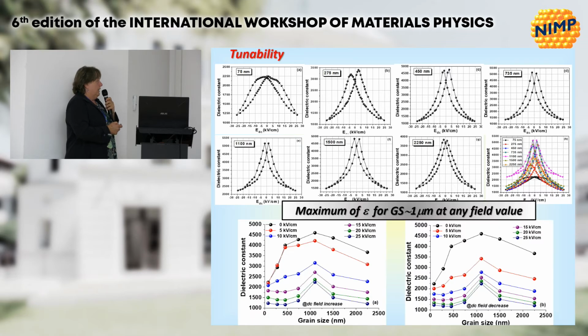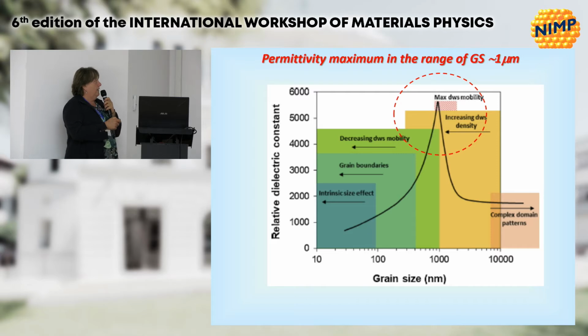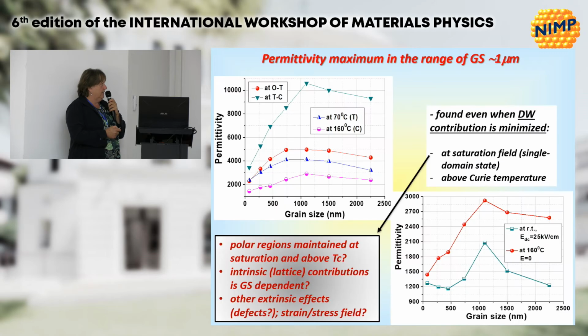And tunability shows us something very nice: the fact that even at high field, this maximum is preserved, which puts questions about the role of domain walls, because what kind of domain walls can one have close to the saturation? If you look, this pink curve is always up, even to very high fields. And the interpretation related to the role of domain walls maybe should be questioned again.